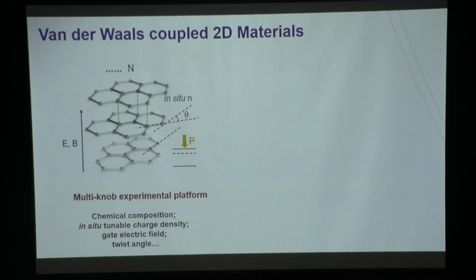For example, graphene is a 2D semimetal, and you can have 2D semiconductors, 2D magnets, 2D superconductors, and you have an unprecedented opportunity to assemble them into a heterostructure where you can control the layer number, the chemical species, and the twisting angle between these layers. So you can invent materials that were not allowed to happen when you throw atoms into a furnace, and you hope the interaction between these adjacent layers is going to give you something that's absent from each of the ingredients. So something emergent from the interaction between these layers.